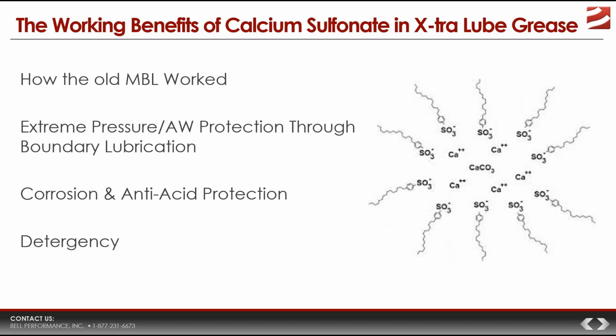One thing we mentioned when talking about the oil additive X-tra Lube is that this boundary lubrication mechanism is the same kind of mechanism that ZDDP used for many years. ZDDP, zinc dialkyl dithiophosphate, was the go-to extreme pressure protection additive in motor oils for decades, the gold standard, because it did a really good job of protecting against wear in extreme pressure situations, and it did it by exactly this same mechanism. So the calcium sulfonate in X-tra Lube Grease protects in exactly the same way that ZDDP would protect in motor oil.